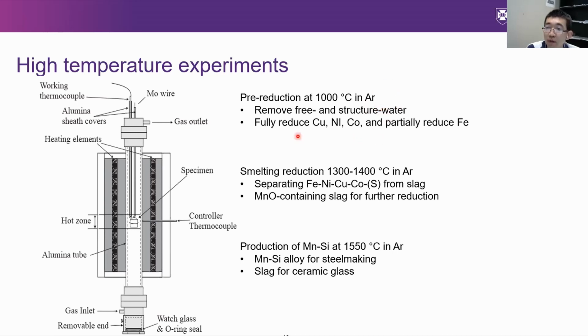So in the pre-reduction of the nodules at 1000 degrees in argon gas, we dry the nodule, and also pre-reduce the copper, nickel, cobalt, and partially reduce the iron, just to achieve a high recovery rate of these metals. And then in the smelting reduction, we complete the reduction and separate the alloys and the slag, and then leave the manganese-rich slag for further smelting reduction.